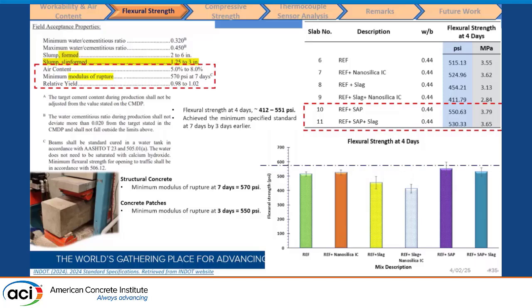The Indiana Department of Transportation standard specification for modulus of rupture at 7 days is 570 psi, and that's for structural concrete. They also made provision for concrete patches for pavements and bridge decks at 550 psi at 3 days.